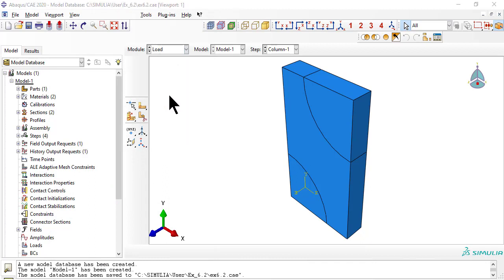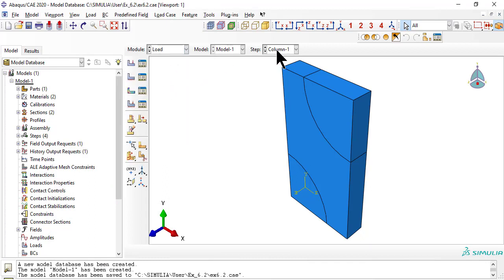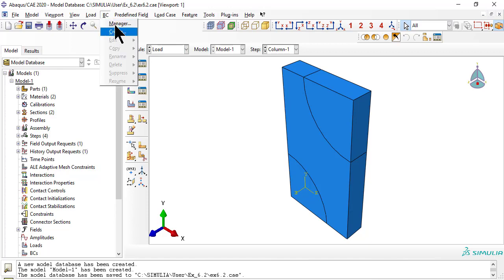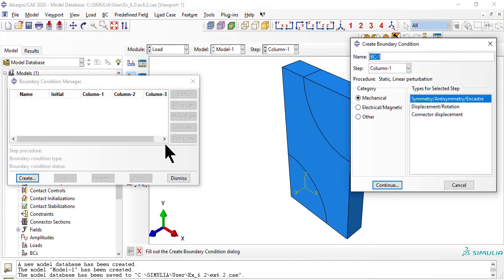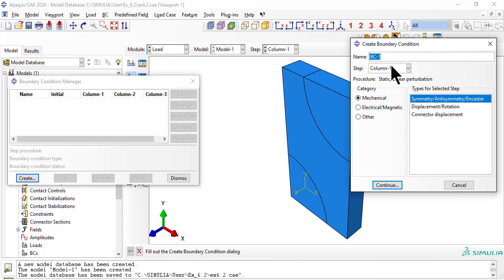For each step, corresponding to each column in the matrix equation, we add boundary conditions that are specific for the current step. We apply symmetry boundary conditions on all faces except the loaded one, which effectively provide periodicity conditions for the representative volume element, RVE.